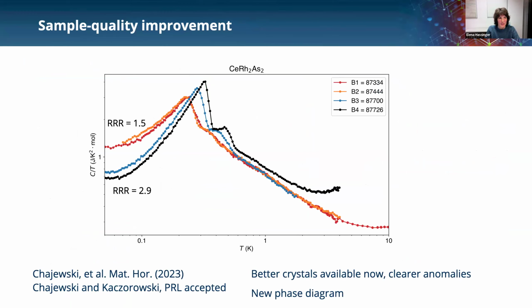I want to show you here that the sample quality has improved since the beginning. So these were the first measurements on first batches. And now we have two new generations of crystals which have clearly increased transition temperatures for both Tc and T0, and also much sharper anomalies. And the quality of this sample is the same as the one from the Poland group, where these two papers have been published. The RRR is still not very good in these samples. It's only 3 in the best samples we have.